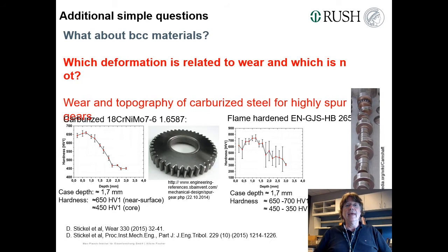So, in mechanical engineering, most parts are made not from FCC, this is by far too expensive, but from BCC materials, like martensite. So, gears, for instance, are mostly made of carburized steel, so you have a high hardness at the surface, and you have, for ductility and some safety, a lower hardness but higher toughness in the core. The same is true, for instance, for shafts, where the bigger ones are made from cast irons. You can do flame hardening, which more or less gets the same thing, but cast irons are like cast irons are, with a lot of scatter.